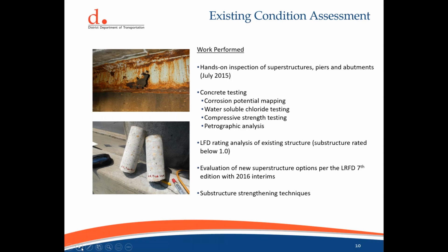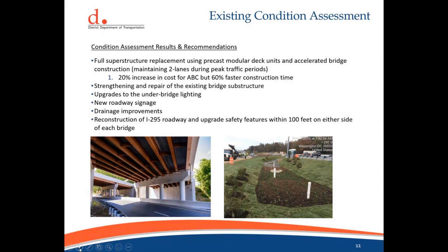So all this leads to the LFD rating. During the rating, the existing structure was rating below a 1 for LFD, which certainly wouldn't do if the structure were to be brought up to LRFD standards, which was one of the goals. For the substructure strength, we thought about several techniques on how to increase the existing condition, and we were thinking of techniques like carbon fiber wrapping, your conventional concrete repair and some crack injection type work. So our recommendations were to replace, obviously, the existing superstructure and rehabilitate the substructure.